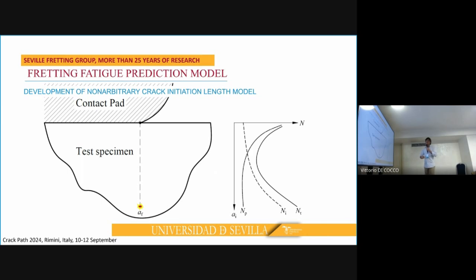You can repeat the procedure for different crack initiation lengths, and thus obtaining a fatigue curve that gives you the total number of cycles as a function of the assumed crack initiation length. From all the possibilities, we consider that crack initiation length giving the minimum total life. And this is the crack initiation length, and this is the total fatigue life of the specimen.